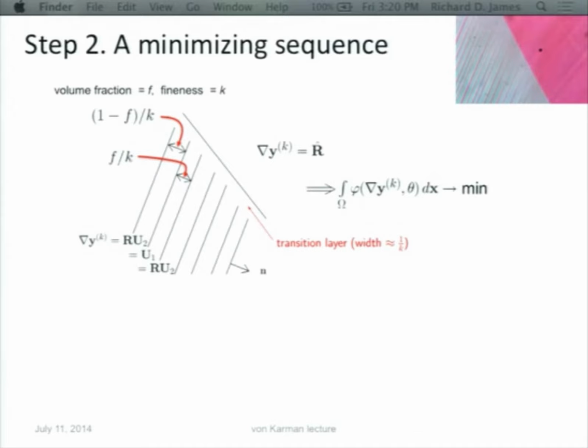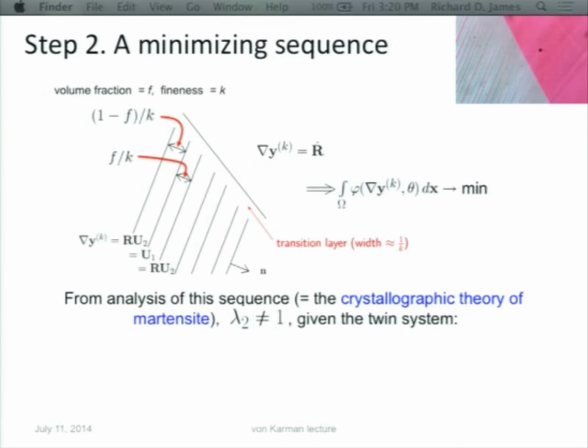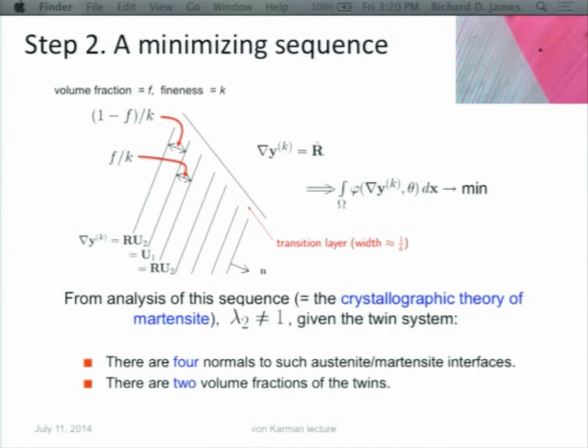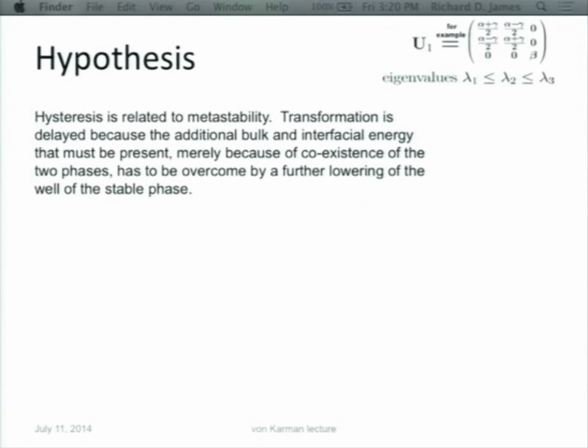But the bottom line in terms of this picture is that the theory without interfacial energy gets all the geometry quite nice. It misses the fineness, and the end result is there's energy in this picture. There's bulk energy in this transition layer, and there's interfacial energy on these bands, and what you see in the picture is a compromise between those two. Okay, and as I said, it's quite a rigorous calculation.